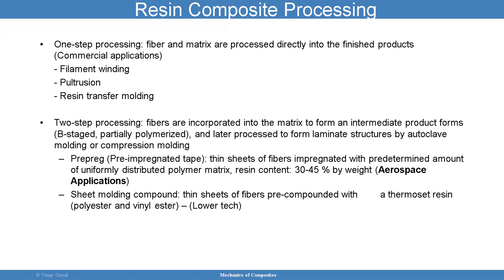So two-step process: first, fibers are incorporated into the matrix in the intermediate product. Then it's partially cured, right? And then I'm going to put all the lamina together to form the laminate, which is going to be made up of a bunch of lamina at different ply angles. And when I say ply angles, what I'm really talking about is that the fiber orientation from lamina to lamina can be different. And I discussed some of that in the previous lecture, in the introductory lecture.